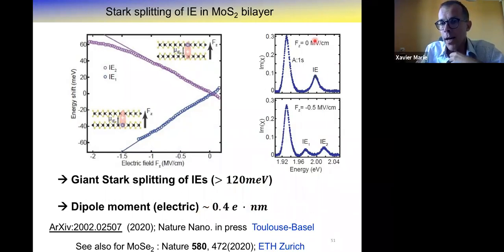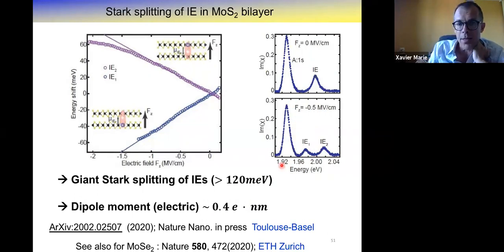So here, again, is an illustration. At zero electric field, you have the A exciton and the interlayer exciton. At 0.5 megavolt per centimeter, you have lifted the degeneracy between the two interlayer excitons, and you really control its energy state, whereas the A exciton, as expected, does not move.